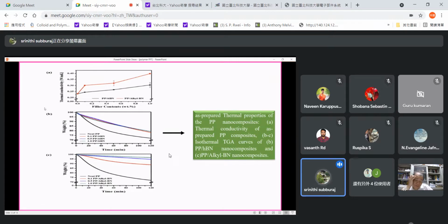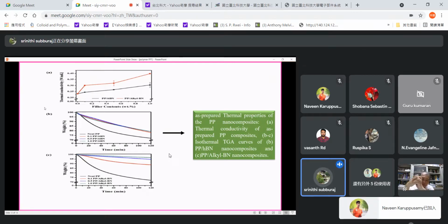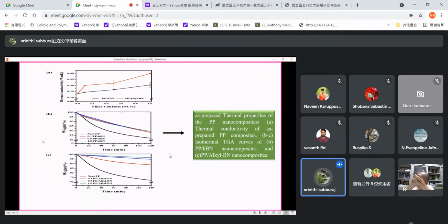The thermal stability of the polypropylene nanocomposite is improved by the thermally stable HBN-based filler. The residual weight of the prepared nanocomposite is much larger than that of polypropylene. When the HBN content increases to the specified weight percentage, the thermal stability increases. The alkyl composite shows the same at different percentages respectively. So again, the nanocomposite shows larger residual weight than the pure polypropylene at the same concentration of filler due to the enhanced stability.